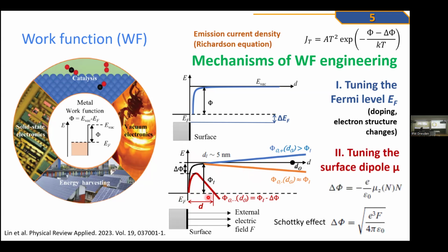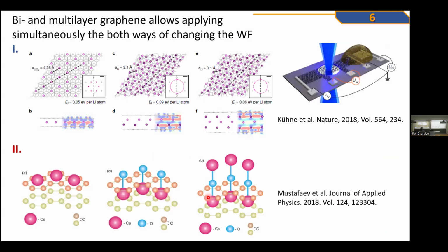Second, results similar to the Schottky effect can be obtained by creating a surface dipole moment, which generates its own electric field, which can increase or decrease the work function of the material. And multi-layer graphene allows the simultaneous application of both mechanisms of work function changing.